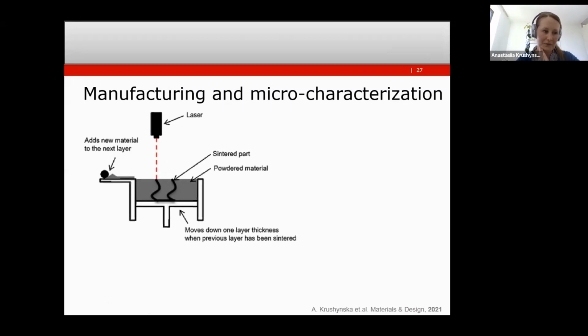So I had a collaborative project with University of Delft and one Swiss university, and they 3D printed a metallic structure, which was quite lengthy in this direction. And until they changed the printing direction, they always had failure modes during the initial excitation cycle. And then we realized that this is due to the difference in the material properties, and then they had to print the structure in the rotated direction to get rid of that dependence on the material density.